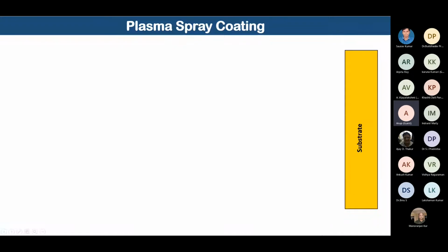Now, on the extreme right-hand side you are seeing the substrate. This substrate could be a metallic substrate, and over it, let me show you a small animation. These are the powder particles; we procure the ceramic powder particles from outside, as per our needs, depending on the coatings we have to make. This ceramic powder particle gets completely melted in the plasma, and once it melts, we accelerate it towards the substrate, where it bombards the substrate. You can see that this spherical powder particle flattens over the substrate, and then it gets resolidified.